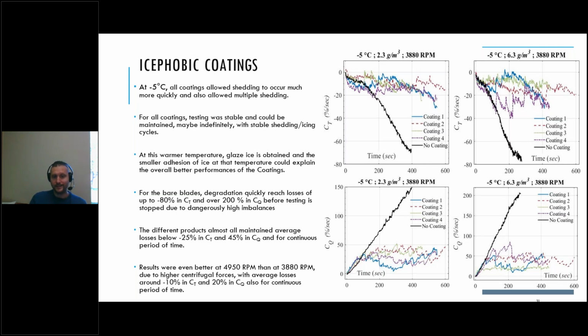So since the adhesion of the ice on the substrate is far lower, the ice shedding events occur much quicker. So the degradation of the performances is much lower when the shedding occurs, but also there's less ice. The mass of ice is much less on the blade. So when the shedding occurs, there's less imbalance, and we are below the safety limit, and we're able to pursue testing.